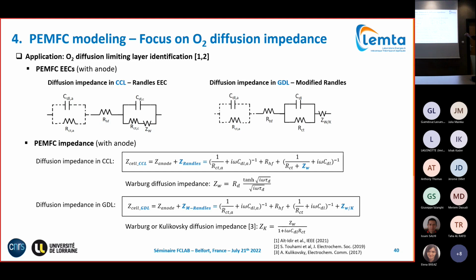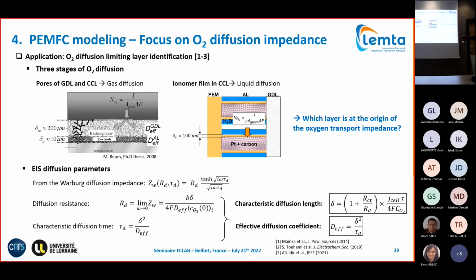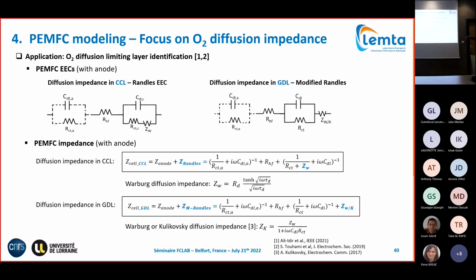And solid lines are associated with the cathode side. So the question to ask is where the diffusion is located: the catalyst layer, the ionomer layer, or the GDL. The Randles circuit, where the Warburg diffusion impedance is connected directly in series to the charge transfer resistance, implies that your diffusion impedance is linked to the catalyst layer. That means liquid diffusion in the ionomer layer or gaseous diffusion inside the pores of your catalyst layer. But if it were the GDL, it would be physically more convenient to take the diffusion impedance outside the circuit of the oxygen reduction kinetics and put it in series.